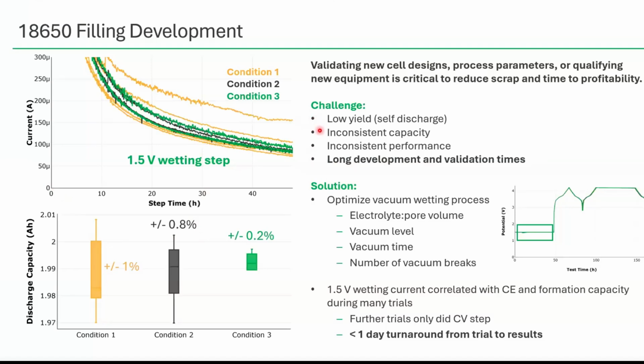What we actually found is if we did our standard formation procedure that we do on a lot of cells here, during what we call a wetting step, where we do a 1.5 volt voltage hold, we found that with UHPC, by looking closely at the current during this hold, we were able to see at very small current levels differences in the spread of the current. This gave us really good insight into how much material was still needing to be accessed and wetted at a certain amount of time into the wetting procedure. This correlated really well later with the consistency in cell capacity, performance and rate testing, and in cycle life.